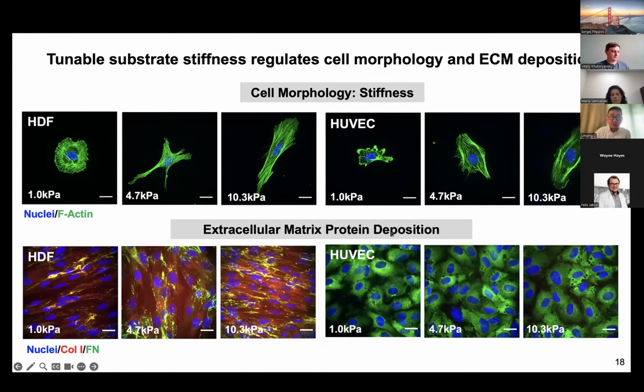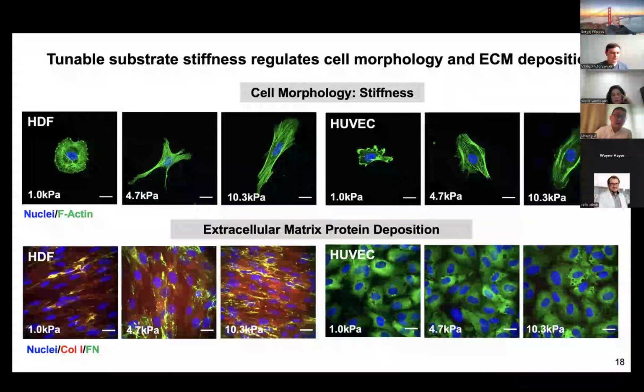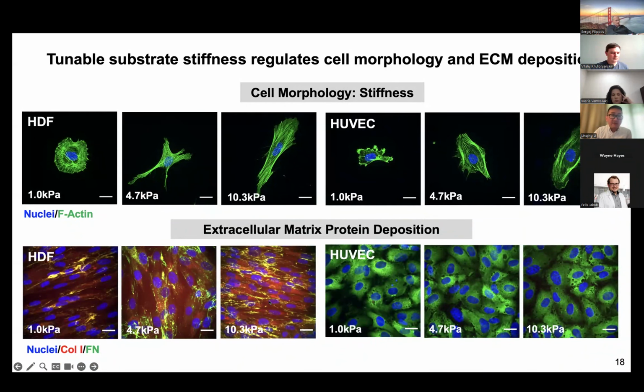Then we're looking at function, at how much ECM protein is deposited by the cells. We grow the cells into a monolayer and look at the ECM deposition. The red is antibody staining for collagen 1, and green indicates fibronectin. In the fibroblast cases, you can see a direct correlation with increased stiffness. You have increased signal for both fibronectin and collagen, which shows that increasing the stiffness increases ECM deposition, which is the onset of fibrosis, as has been previously demonstrated.